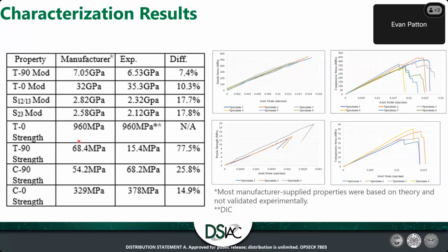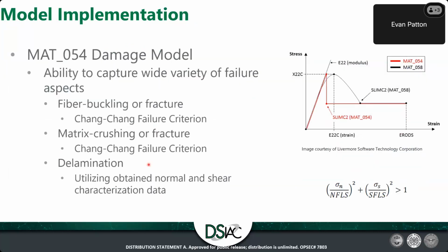This theory is based on what's called multi-mechanics, I believe, which is a representative volume element, where you feed it a bunch of different properties for the individual fiber and the individual matrix, compound it into one system, and do a virtual tensile or compression test on it to get these results. So it's very idealized and nowhere near close to an experimental setup. If you're blindly throwing in these values, you're playing with fire a little bit. It's a pain to experimentally derive those mechanical properties, but in the end, it's going to be worth it when you implement them into the model.